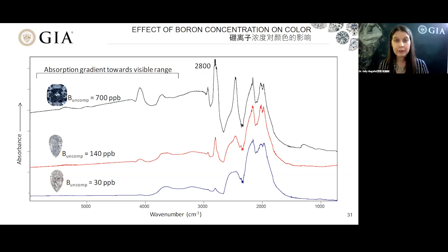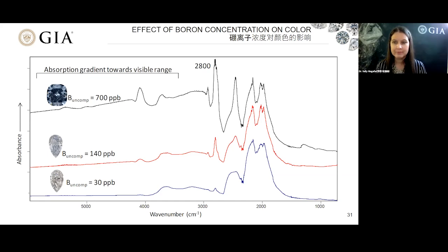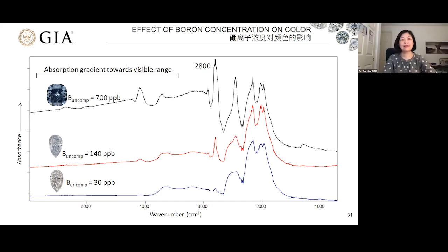Now, this isn't a perfect correlation, and there's certainly some exceptions, but generally, the more boron you have, the deeper the blue color. It doesn't take a lot of boron to have a pronounced effect on the color of these diamonds. 另外这张图还能告诉您，硼的含量和颜色也有关。一般来说，硼的含量越高，颜色越深。您可以看3个硼的含量越来越高，越往上越高。不是100%的对应关系，但基本上通常是这种情况。其实硼只要出现在钻石里边，很少的量就可以把钻石变成蓝色。